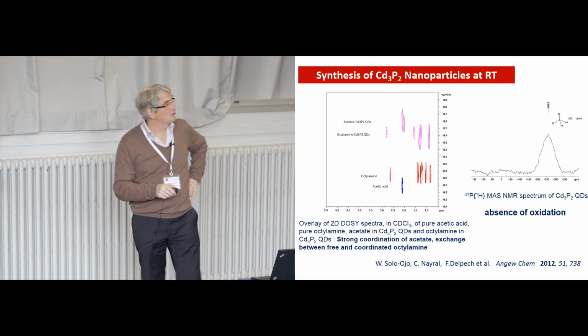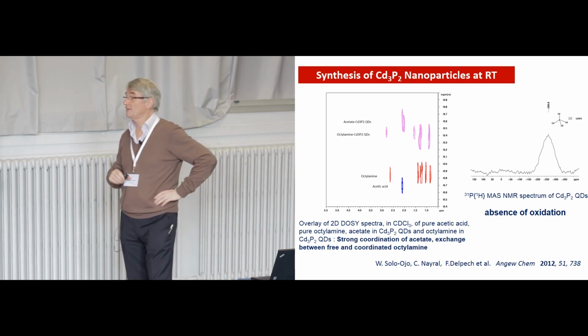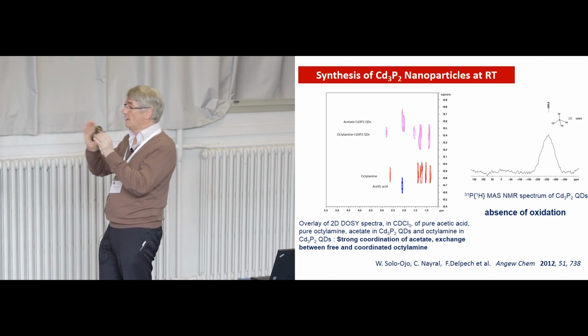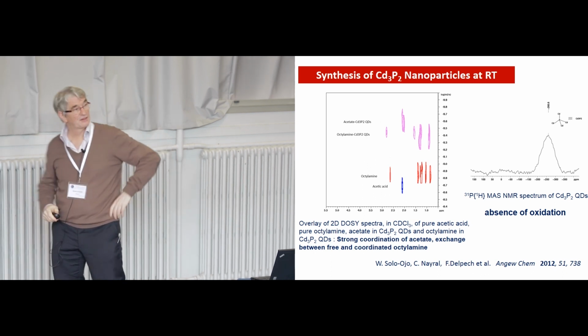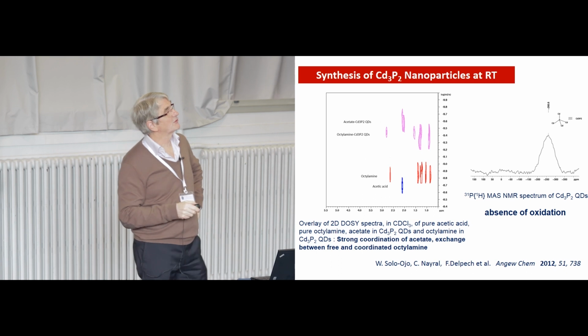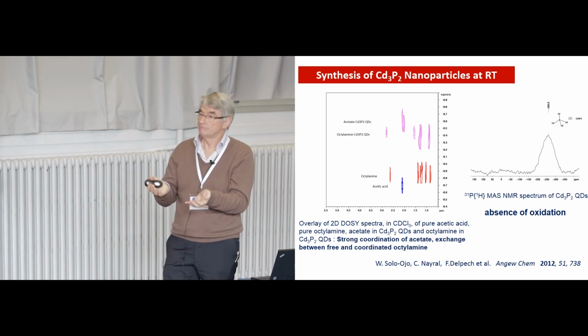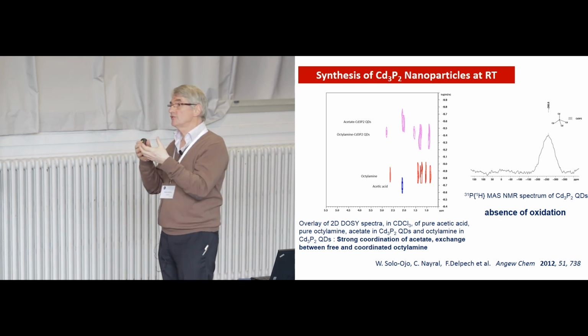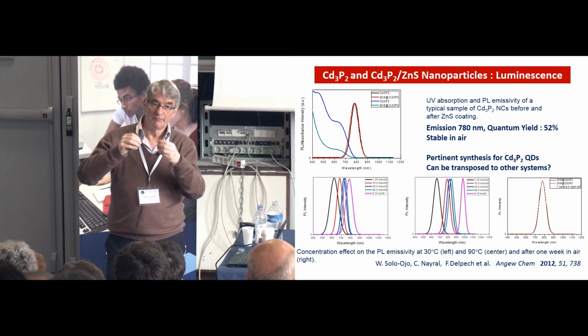Since there is no oxidation, you can adjust the size that you see by adjusting the luminescence. And you can work even at 90 degrees to heat a little bit, and you can adjust the size of the particle. The good thing also is that you can grow, well, not a zinc sulfide layer, but put...